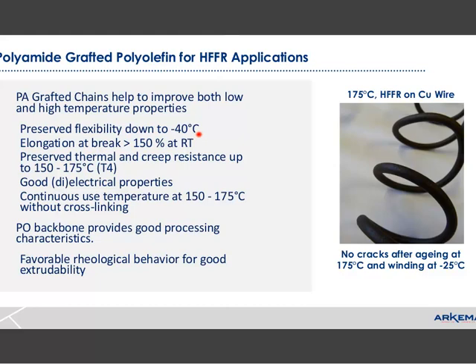The area that I see these materials being used is in HFFR applications. The primary benefit here is that you have a good balance of properties. We have very low temperature, very high elongations, and what's important here is that the continuous use temperature of 150 degrees C without any cross-linking can be attained with these particular materials.